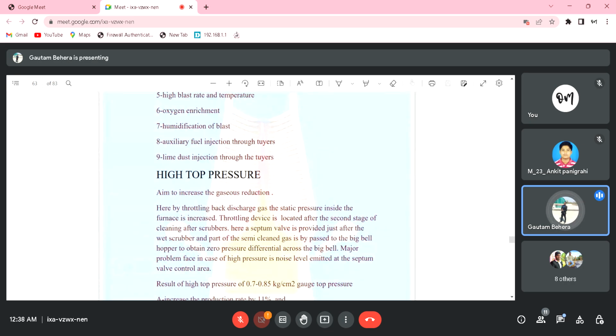Why? Because, I told you, we are injecting PCI through the tuyere. If you inject more PCI, more silica will come out, and that will go into the slag. So more SiO2 means more acidic, because SiO2 is acidic, FeO is a weak base, and CaO is a strong base. Right? You have to remember these points. And Al2O3 is an amphoteric oxide. So primary slag is FeO.SiO2.Al2O3, which is acidic. Why? Because FeO is a weak base, but SiO2 is a strong acid.